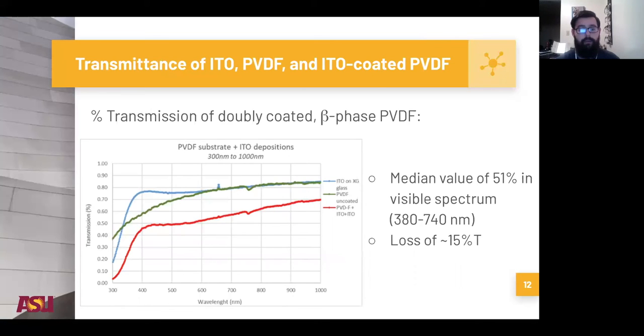So here we can see our results from our ellipsometry. We see our percent transmission as a function of wavelength. The curve we want to pay attention to is the red curve with PVDF with ITO coated on both sides. And we want to compare that to the green curve with uncoated PVDF. We see the median value for our coated PVDF is 51%. And when we compare that to our green uncoated curve, we see a loss of 15% transparency.